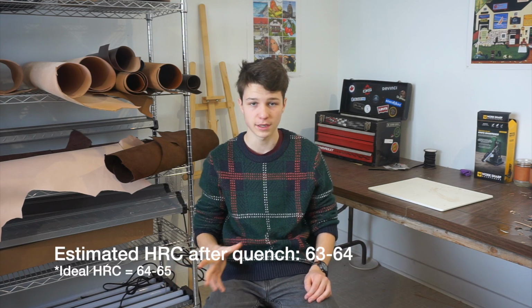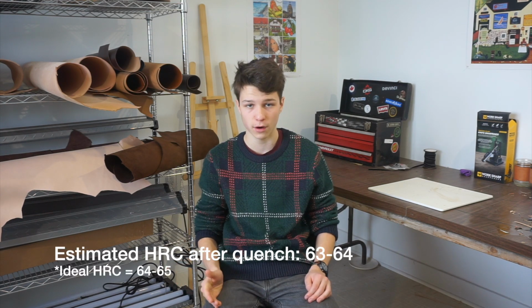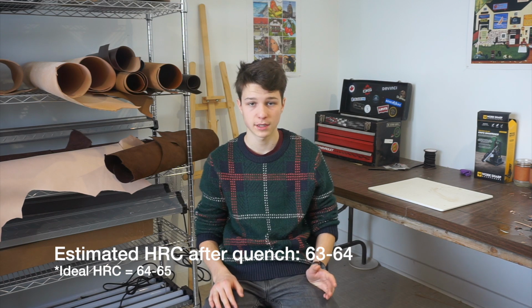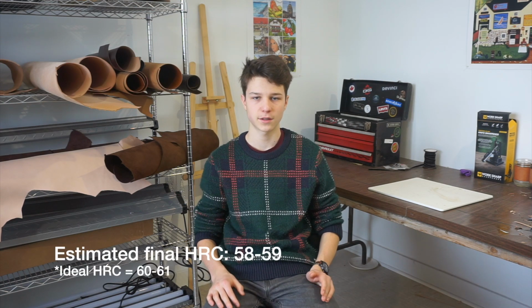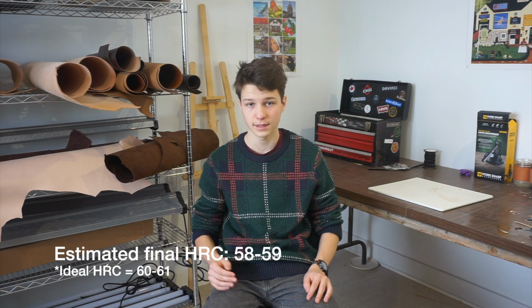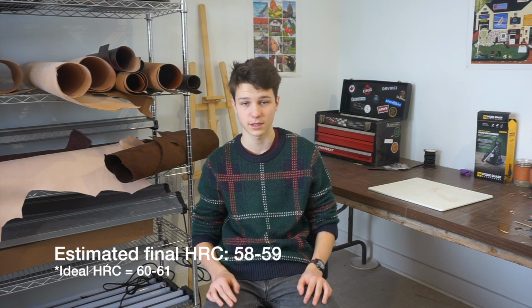I have no Rockwell gauge, but I would estimate the HRC, or hardness level, of the steel after quench to be 63 to 64, the ideal HRC being 64 to 65. And after tempering, I would estimate the final hardness to be 58 to 59 HRC, ideally being 60 to 61.